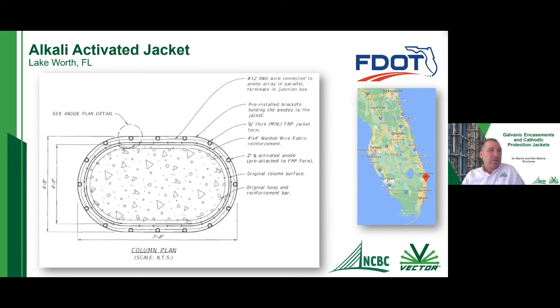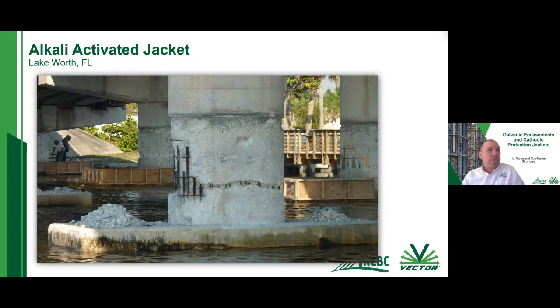And then there was some welded wire fabric also being used just to help for confinement. And then the anodes were being placed inside of here. And then the jacket was just filled with mortar. So first thing you do when you come in is remove any of the delaminated concrete. So you can see here, the delaminated concrete was removed, and then you can see there's a continuity groove.